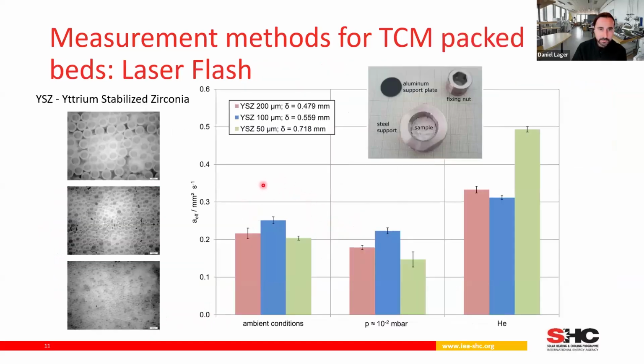So another important thing to know is the so-called thermal diffusivity and thermal conductivity. And why this is important, especially for packed beds, as you have it for thermochemical materials, is the influence of the gaps in between, for example, your powder or your TCM material. I show you here an example with yttrium-stabilized zirconia, so it's a ceramic material.